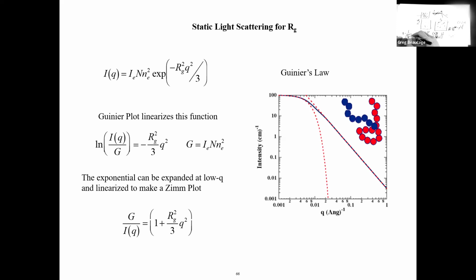If you have a large osmotic compressibility, then they don't want to cluster, so you get no scattering. It determines how many of these dense areas you're going to get. If you have a higher osmotic compressibility, they'll want to disperse more. So 1 over that means you get a smaller intensity for large compressibility, where they're dispersing.